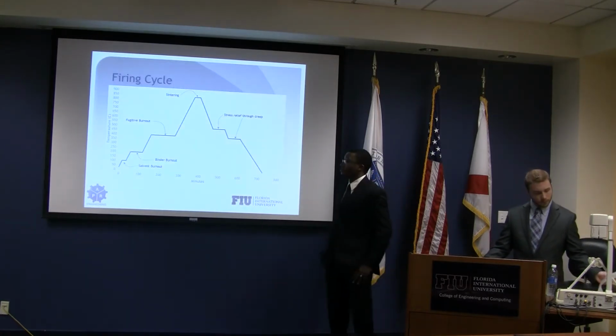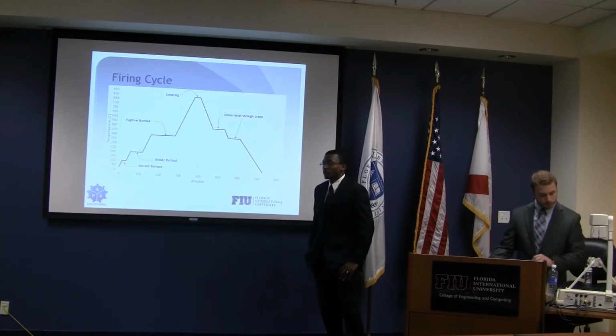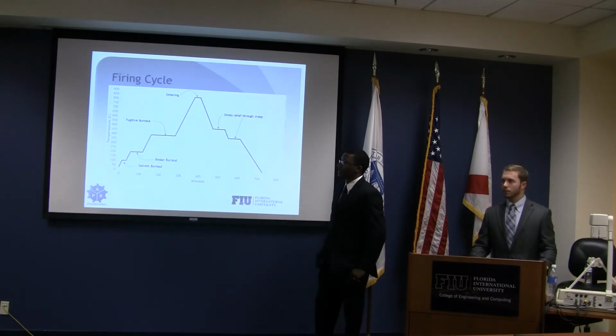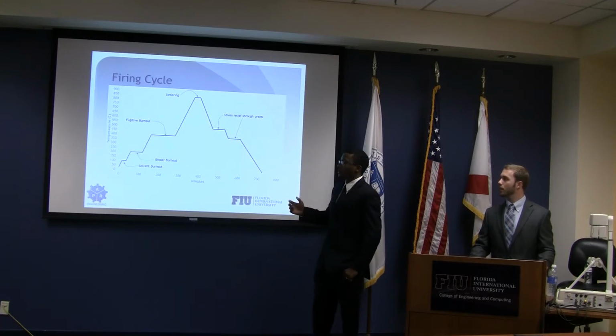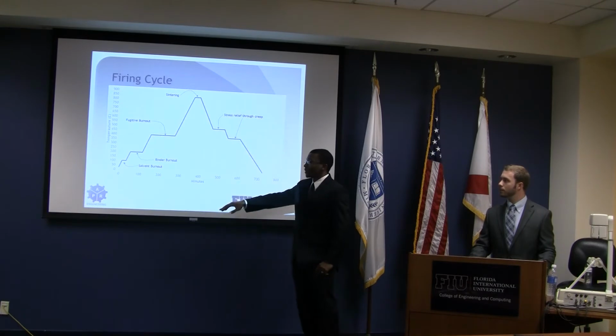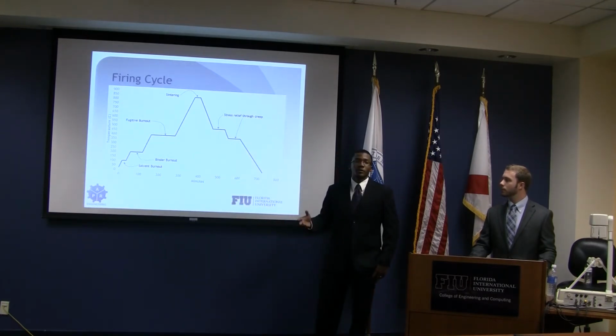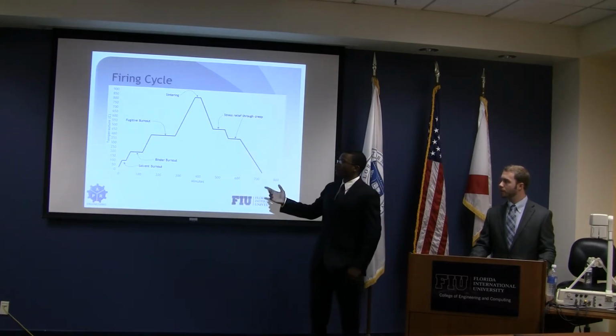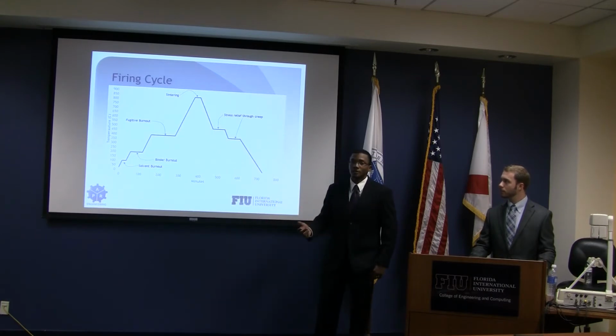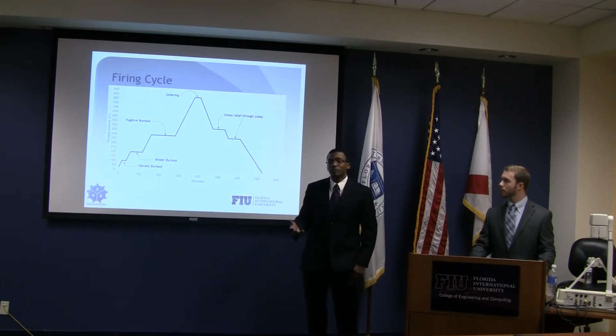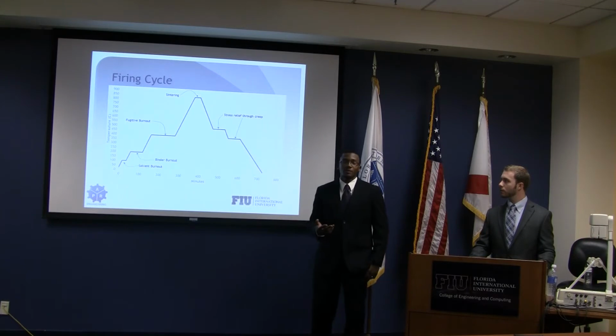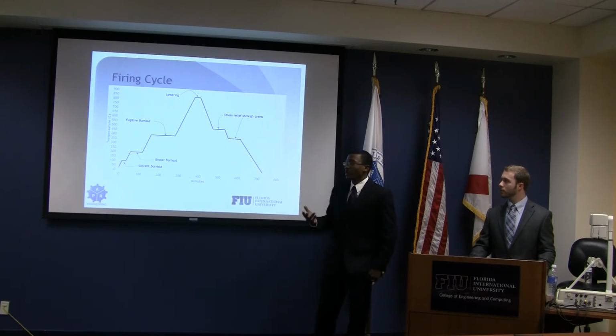This is the firing profile used for the final assembly of the regular device. It is based on the same LTCC firing profile used for DuPont's tapes. Each of these plateaus seen here are different sections where different components of the tape are burnt out. So once the solvent, the binder, and the fugitive materials are burnt out, sintering occurs at the midway process during the peak temperatures. Then the temperatures are ramped down at a steady rate to allow for creep. Creep is an important step because it allows for the relief of thermal stresses at the interfaces when you're firing metals such as silver at 40 to 60% of the melting temperature.